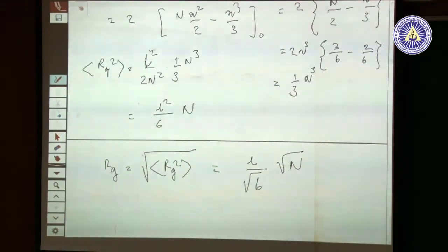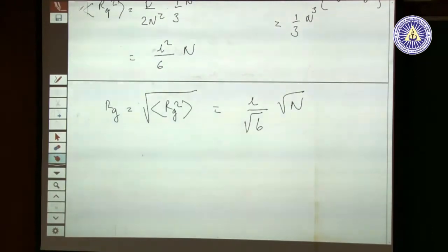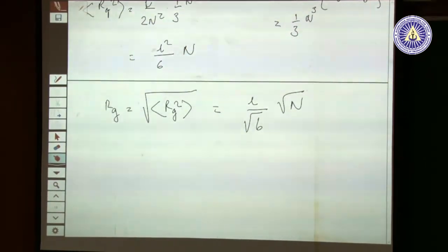So we found a very important aspect of polymer chain statistics and in polymer physics in general. Firstly, the large scale properties, whether it's Rg or Re, are scaling the same way with the degree of polymerization, and n is the degree of polymerization. And the local structure is only entering through the length scale L, which is the bond length or the monomer size.